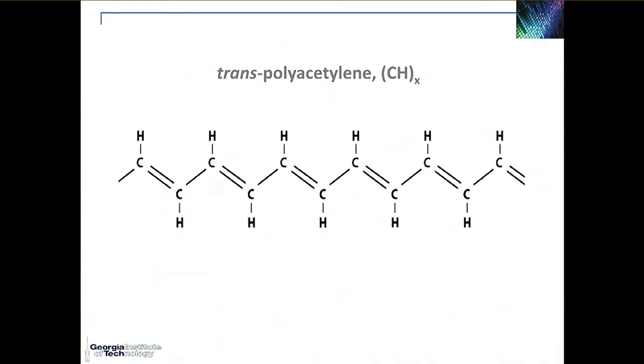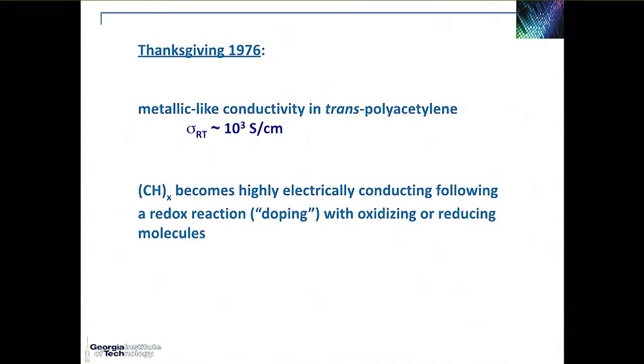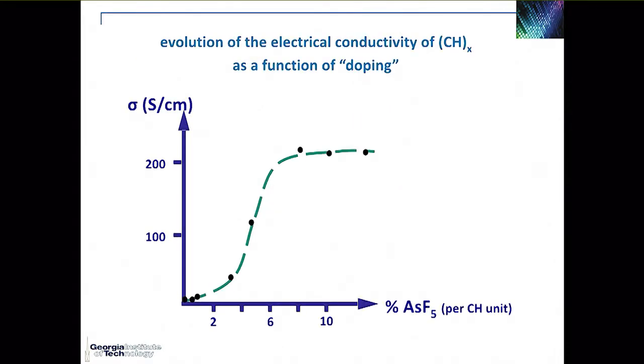So that's really a pi-conjugated organic polymer. Alan MacDiarmid immediately said, well, you have to come to Penn. And the following year, in the fall of '76, Hideki Shirakawa arrived at Penn. And around Thanksgiving that year, following the idea of the oxidation of SNX, they had the idea also of trying to oxidize polyacetylene, and that's how they discovered that in that context, polyacetylene can be made very highly conducting through oxidation or even reduction. And so that's really the start of the modern era of organic electronics, even though, as I said, at the time these were called synthetic metals, with conductivities at the time reaching a few hundreds of Siemens per centimeter.